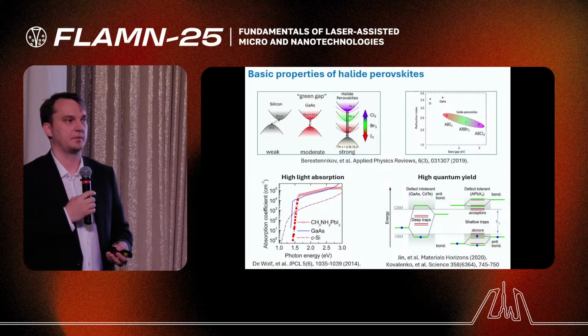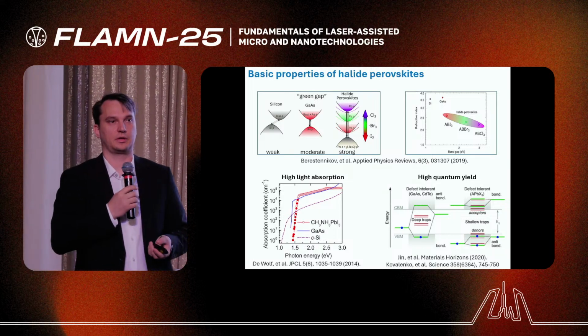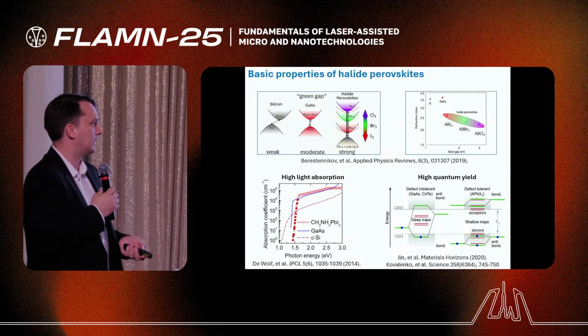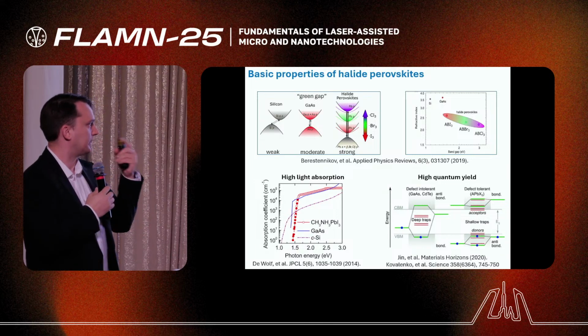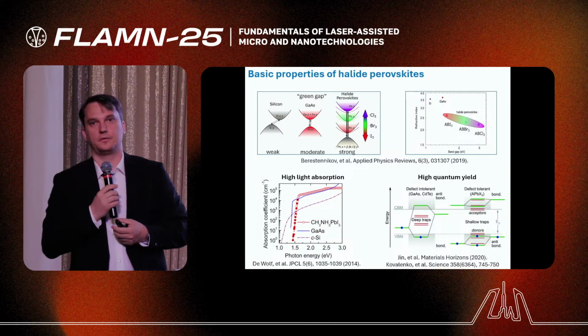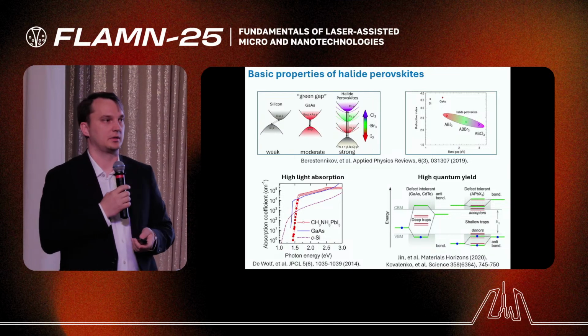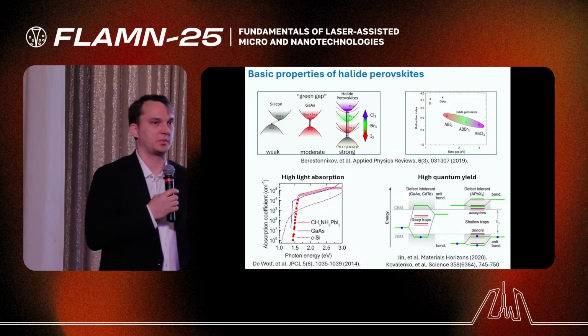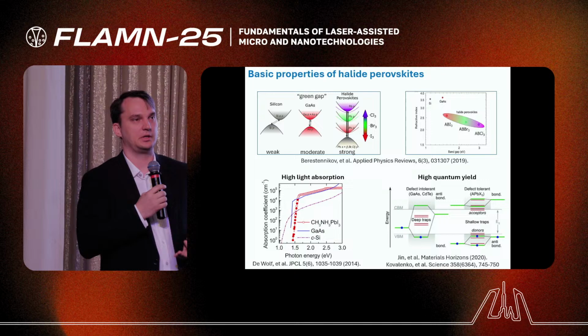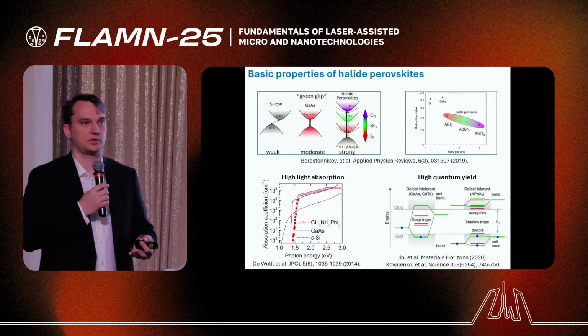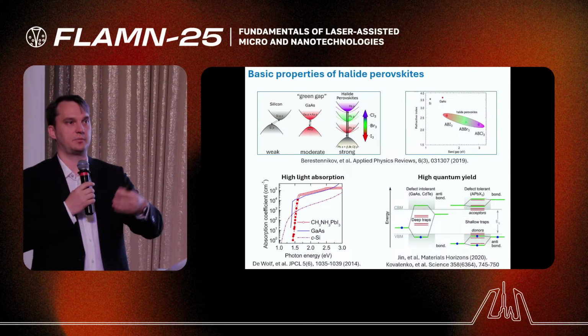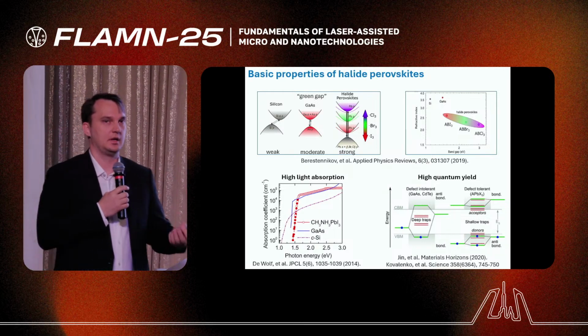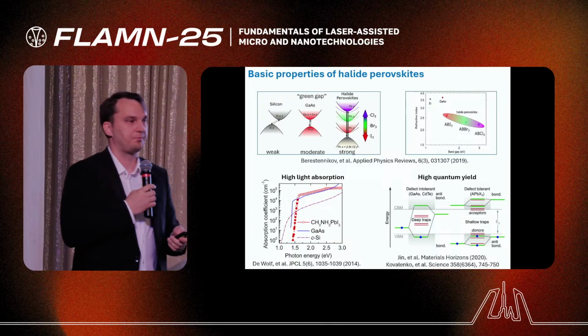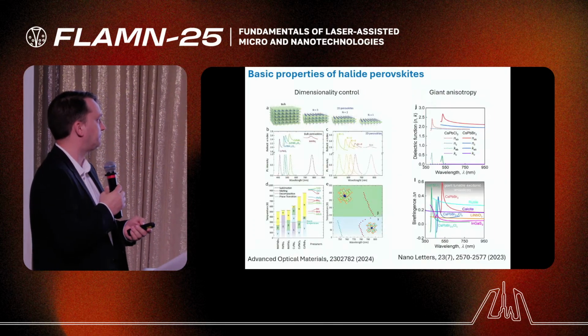It's a direct bandgap semiconductor with a strong exciton at room temperature. Also, interestingly, this is a so-called defect tolerant material, which means that after processing or aging of the material, we have not deep defects but more shallow defects. So the carriers can't be trapped at room temperature, and still we have a high quantum yield for photoluminescence.